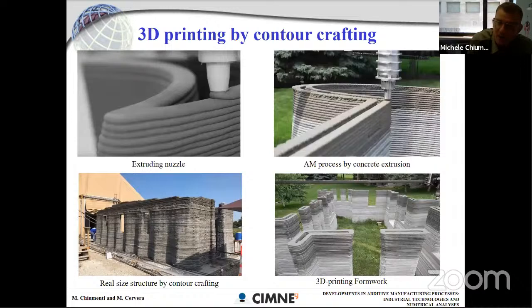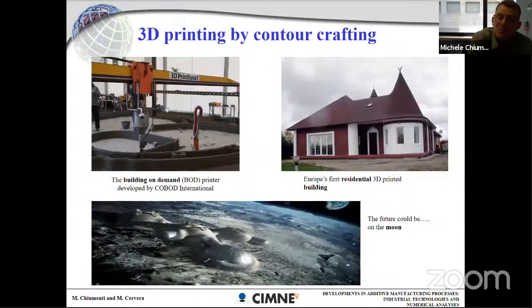Well, contour crafting is very similar to what we were used to in wire feeding. In this case, you have an extruder, which is extruding the material according to a specific scanning sequence, or in this case, deposition sequence. So you have a robotic arm able to generate different layers of material according to a specific sequence. And they have exactly the same problem as for metallic alloy: what is the timing for this deposition? In case of metallic alloy, the problem was temperature. Here, the problem is the hardening of the lower layers.